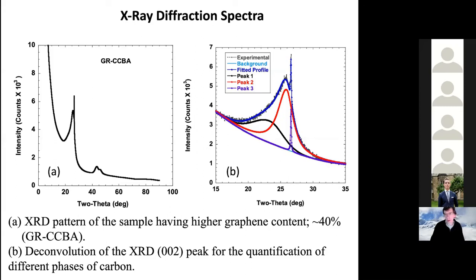So we've taken XRD spectra of these materials produced under the different conditions. You're seeing that here. This would be under a low methane-argon ratio, with deconvolution applied to that main peak. The peak on the right is just an expanded version of that on the left, over a smaller angular range, applying a 2-peak deconvolution profile once the background is subtracted to identify 2 phases, if you will, of different forms of sp2 carbon.